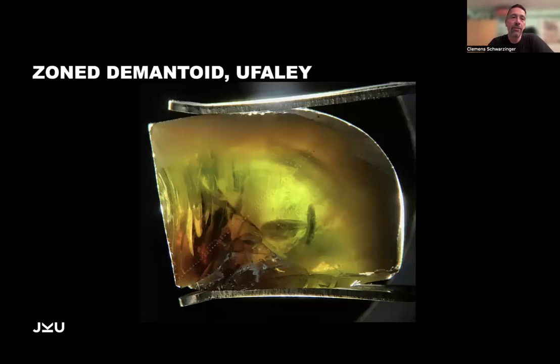Here's an example. We have a nice garnet. It's an andradite. It comes from Russia, from Ufalei. It's greenish. It's an andradite, so we can call it demantoid. And you may see here, these are the spots that we have shot with the laser. And here are two lines running across, starting from the center of the crystal to the outer rim. And we have a couple of different colors in here. Here we have brown, we have intense green, then yellow, and then again some olive colored material. So the question is, what does the chemistry look like along such a crystal?